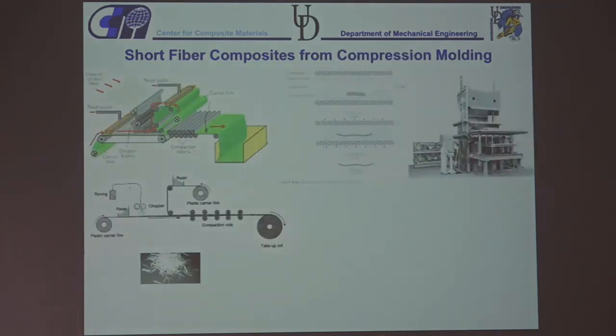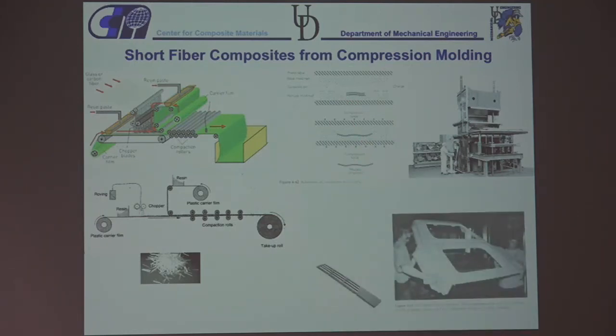And the other short fiber composite process is using SMC, where you have your resin and you chop the fibers in between, and then this becomes your charge that you take to the place where you want to make the composite. You cut it up, you place the charge in the machine, and then you compress it. And you can make pretty large parts like that. So injection molding and compression molding were very widely used for making short fiber composite parts.